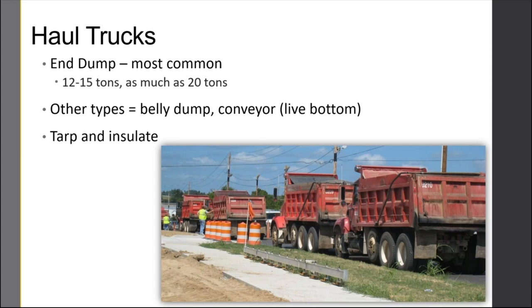There's a mixing temperature at the plant and a compaction temperature — the temperature it needs to be when being placed at the job site. The difference in those two numbers should account for how much cooling will happen between the plant and the job site. If it cools off too much, it's going to be extremely difficult or impossible to compact properly. We need to make sure those trucks are insulated. Not only for temperature concerns but also for safety, they do need to be tarped — covered as they head out to the job site.